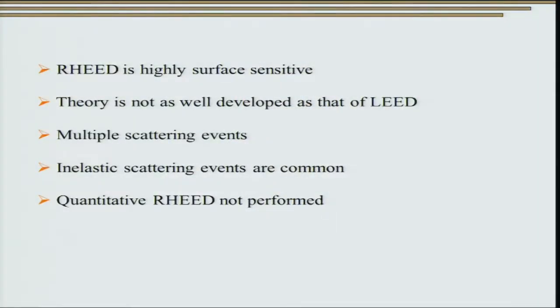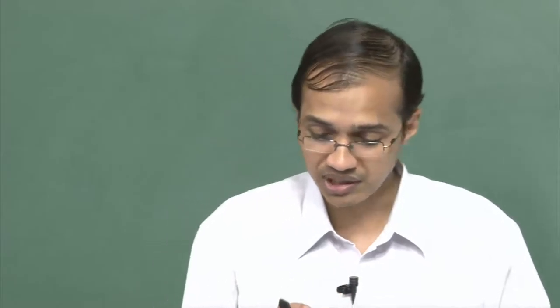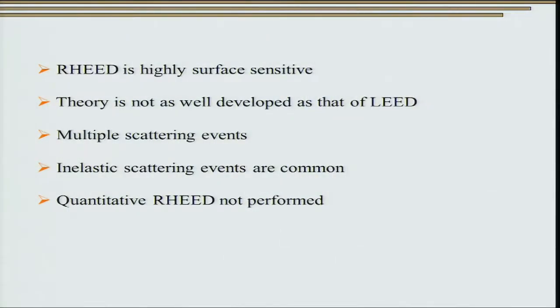The entire focus of reflection high energy electron diffraction is that the technique is highly surface sensitive. However, the theory is not as well developed as for low energy electron diffraction and does not account for multiple scattering events. The technique is also characterized by plenty of inelastic scattering events, and therefore quantitative estimates from reflection high energy electron diffraction have not achieved as widespread use as for low energy electron diffraction.